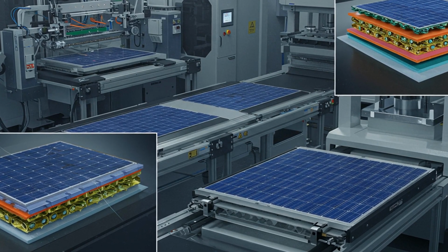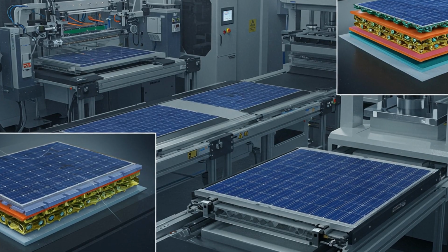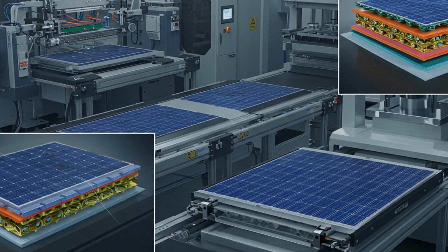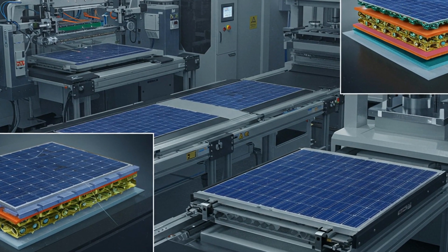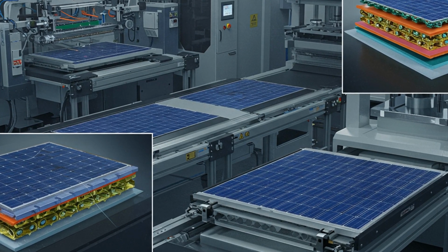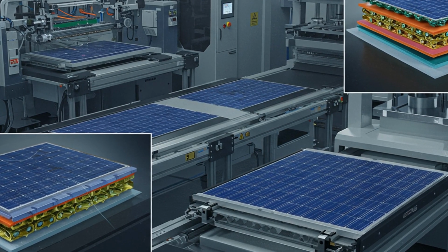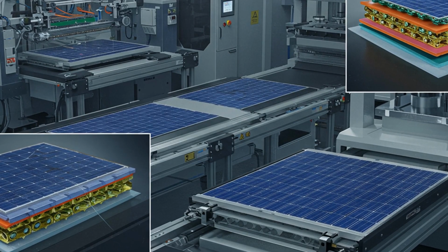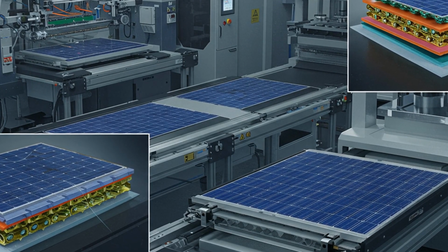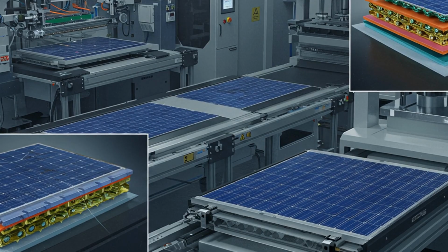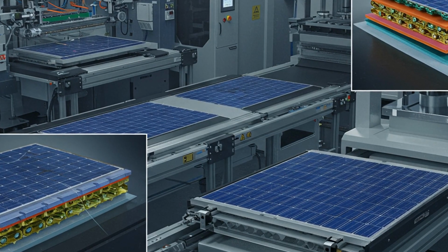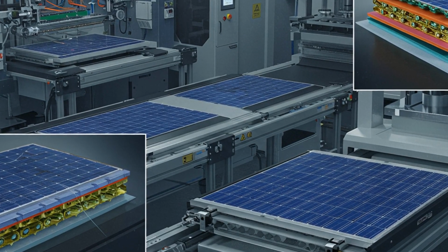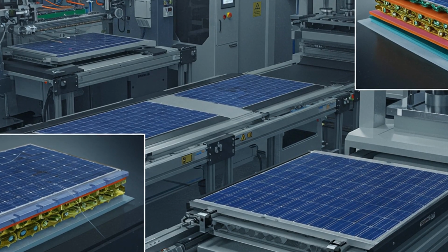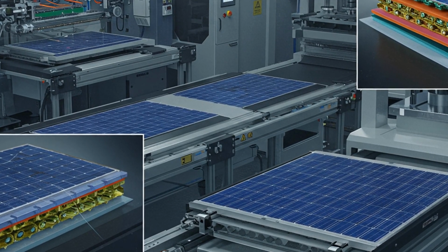This sandwich moves into a lamination press. Under vacuum, the module is heated to roughly 150 degrees Celsius and pressed for 10 to 20 minutes. The encapsulant flows and cures, bonding glass to cells and removing trapped air that would otherwise cause delamination. A junction box is affixed and electrical connections are routed. The module is now weatherproof, ready to be mounted on racks or assembled into arrays. Mechanics, chemistry, and heat meet here to create a long-lived energy product.